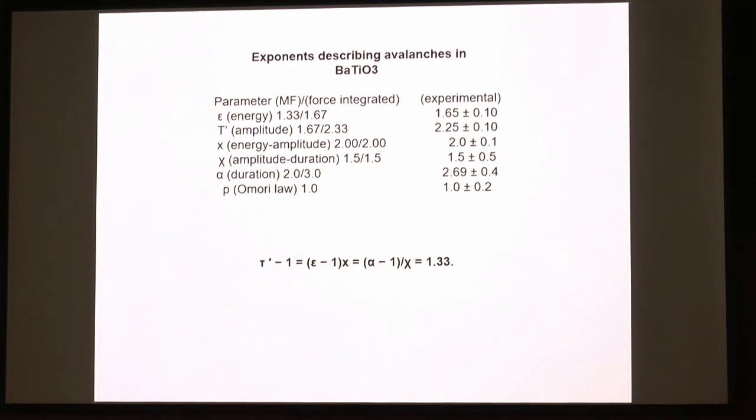So that means that the behavior inside a barium titanate, if you put it in our mind, is predominated by very, very small movements of very small areas near interfaces, right? I mean, it's a power law. The small movements are, with power law probability, more likely than the big movements.